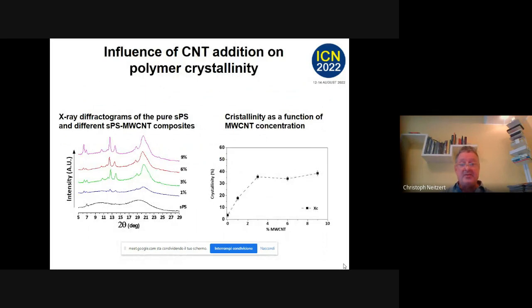No? So here you see, for example, one of the influences. There is a lot of structural characterization. I will not show you. I will concentrate on electrical characterization. No? So you see on the left side, for example, how the X-ray diffractograms change with nanotube concentration, and you see actually that the material becomes more crystalline, no? With this like a threshold value, and then it stays constant. We prepared different concentrations, and here for the application, we will show you just the highest loaded sample with 9% carbon nanotubes.